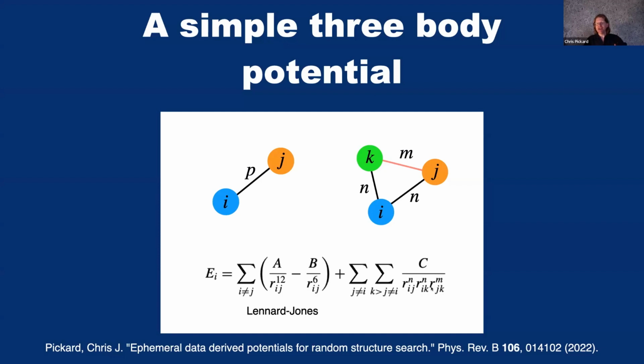And I found I could take this potential and then do a structure search using potentials where I was, by hand, choosing the parameters and looking at what kinds of structures were coming out. And I found that as I adjusted these parameters, the C's and the N's and the M's, I was able sometimes to find, say, the diamond structure. I could get nice open structures, or I could get graphite. Or what really convinced me that it was onto something was when I noticed I could find the alpha boron structure, which is made up of icosahedra of borons.